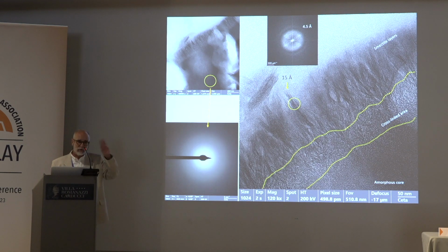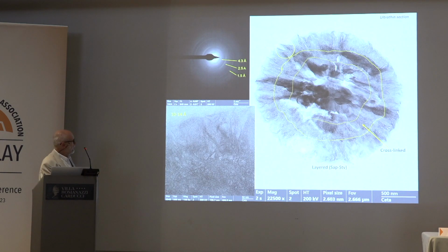So the outside of this is a clay, and this is a sphere. This is an artifact of the diamond knife, so this part, but the core is very small, very reduced, because of the size, we compare the filament and the sphere, but the structure is always the same, the cross-link area and the clay layers.